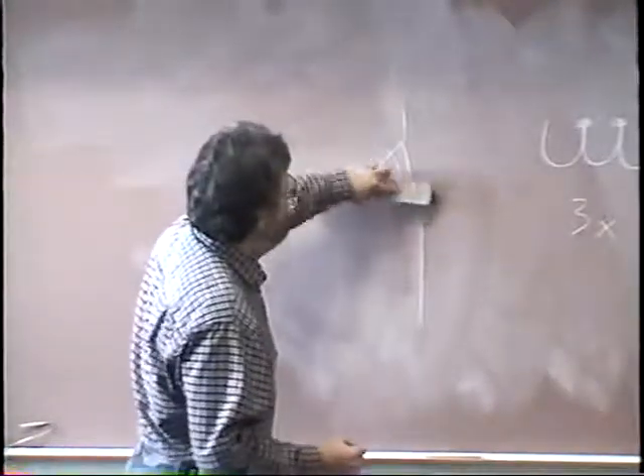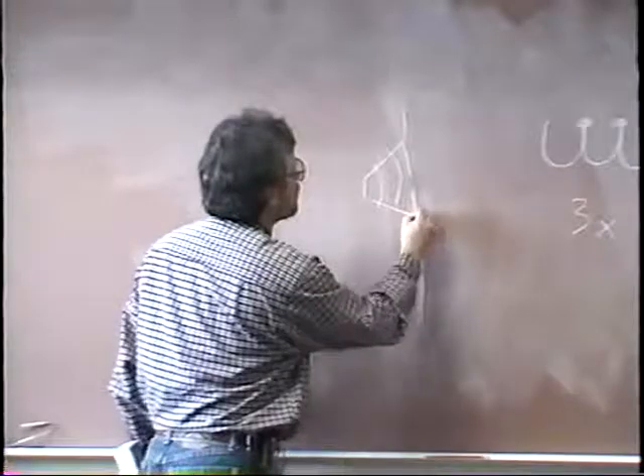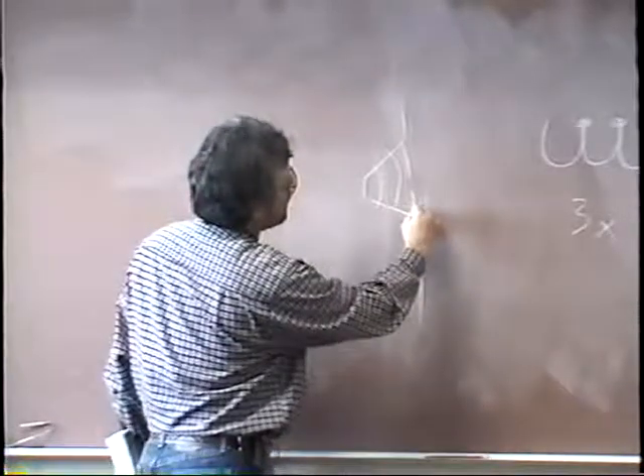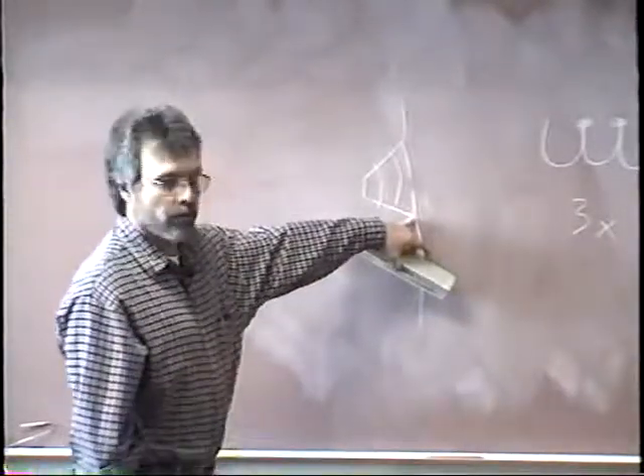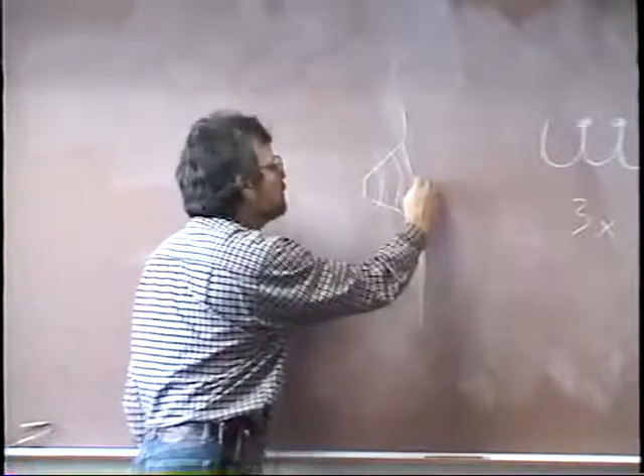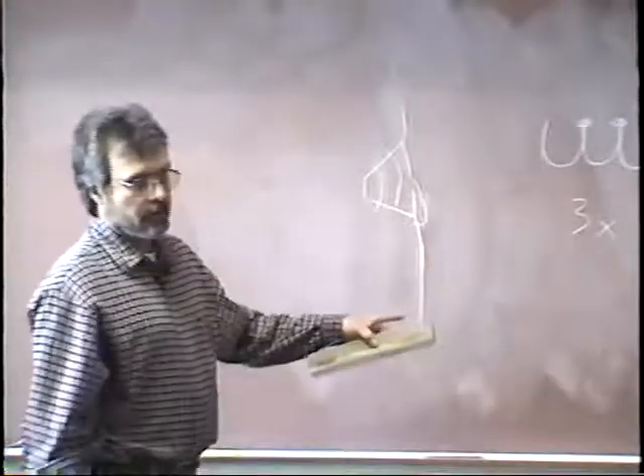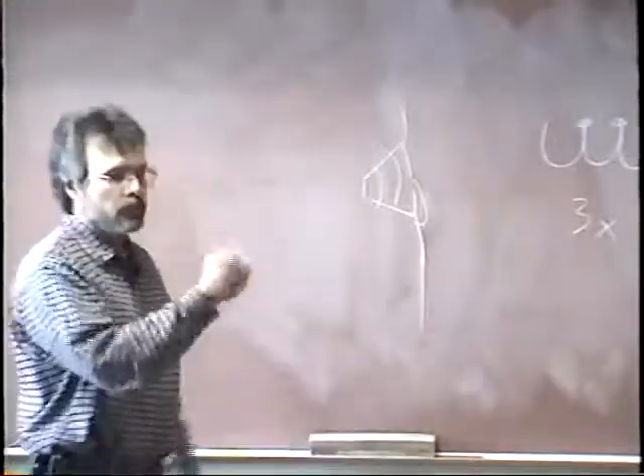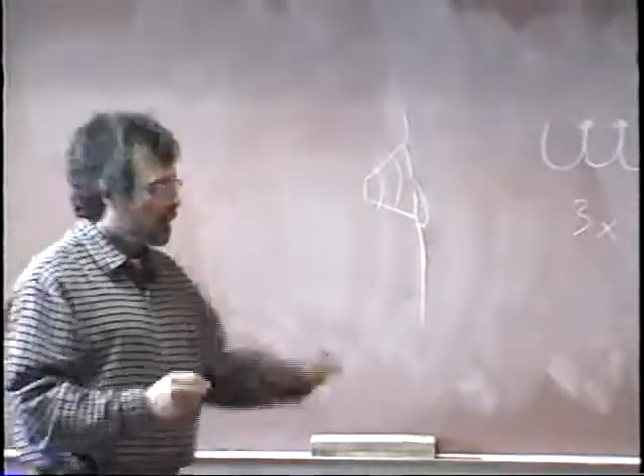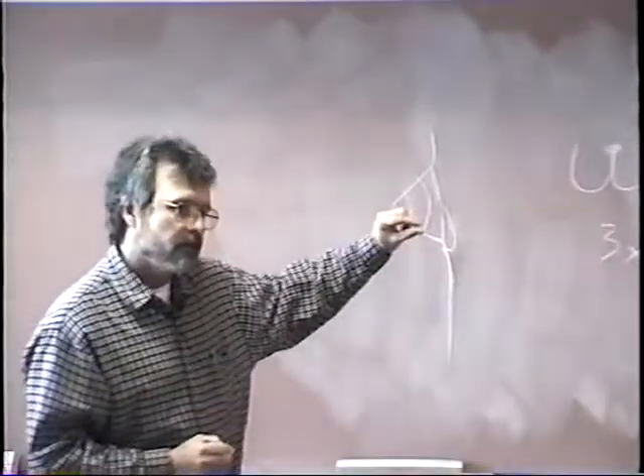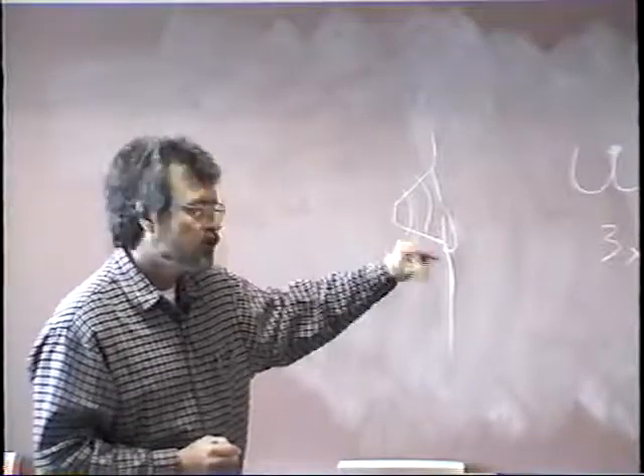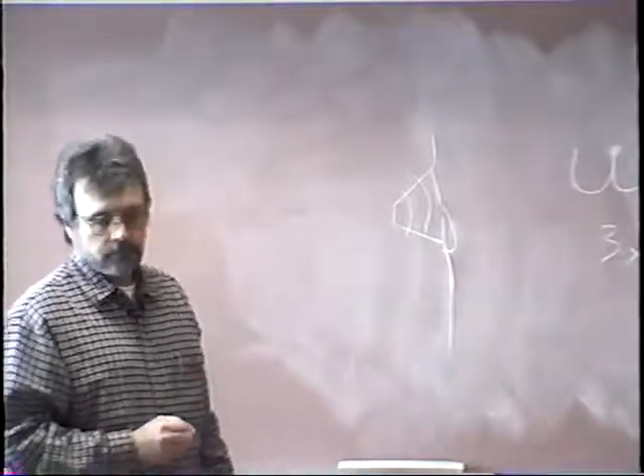If you overfill this bead, if you overfill it to where that filler pass comes all the way out to the edge, or you burn that edge up, then you are likely to get this overlap. But if when you fill that root joint, whether it's plate or pipe, you fill it to within about the thickness of a clear lens from being flush, you won't get that. Okay?